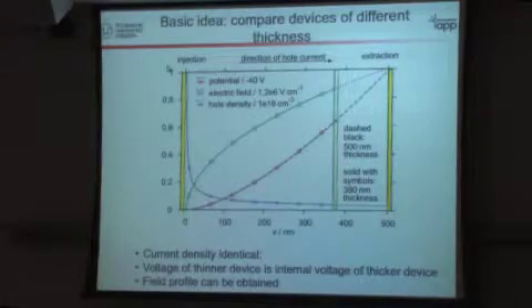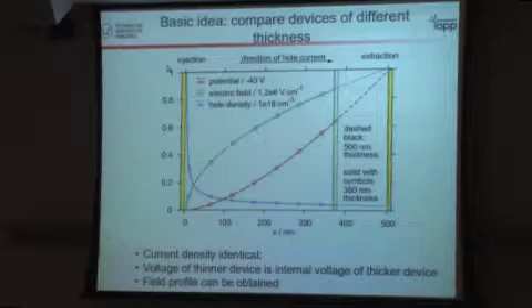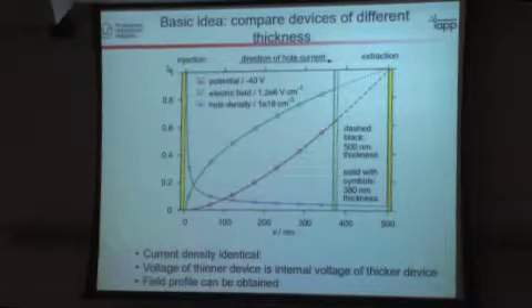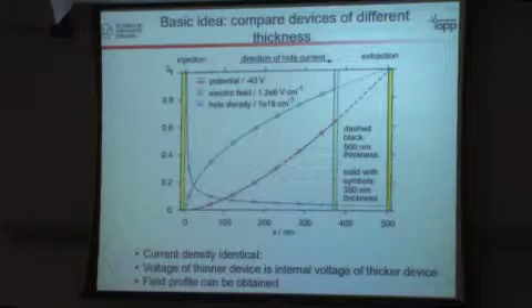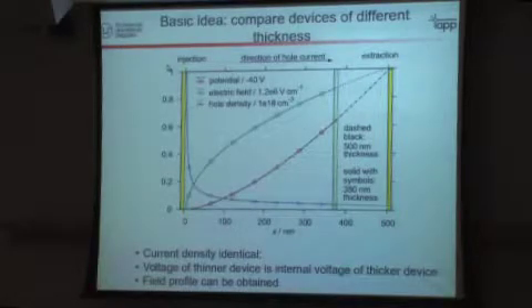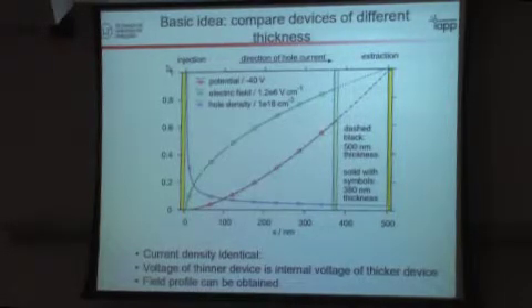The idea behind the model is very simple. Let's assume you have a homogeneous film of a material, and you transport carriers through it, and now you start to slice, so to speak, this material. When you keep the constant current for different thicknesses, for instance, when you go down for this thickness, you need this voltage, and if you go down in thickness to a thinner sample to have the same current, you actually need this voltage. If you go down here, you need, for instance, this voltage. You can actually plot the electric potential in the sample. What you do is you make a series of samples of different thicknesses, and then you measure always the same current, and the voltages directly tell you the potential in the sample.